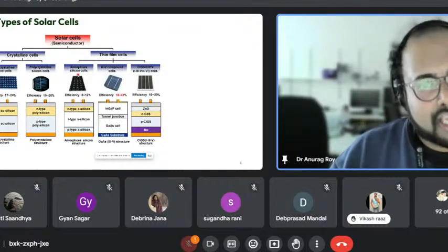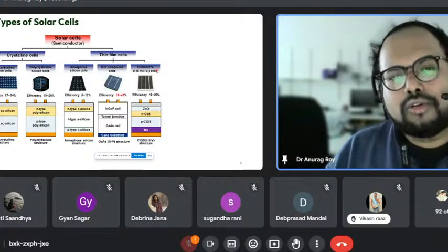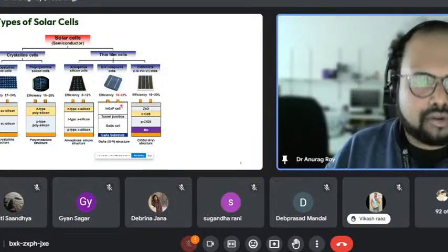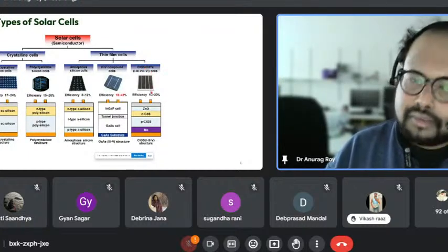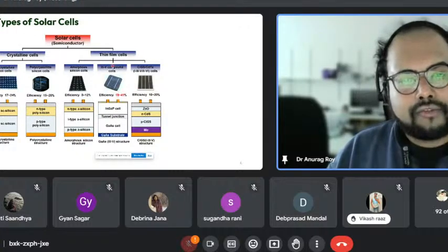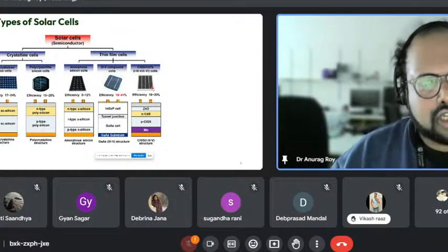And here is one interesting point: if you change the crystal structure of a semiconducting material, it can change the electrical efficiency as well. Another option is to not depend completely on silicon and go to some other materials, called group 3, group 5 compound-based solar cells in the periodic table. These can be indium gallium phosphide-based cells, gallium arsenide cells, CIGS, which is copper indium gallium selenide, and cadmium telluride cells. These cells are also available in the market, and they are also very good. They are called thin film based cells, and efficiencies lie between 18 to 41 for the 3-5 cells, and 10 to 20 for the others. Efficiency also depends on the way we produce the cells, how facilely we produce them, and how the atoms are oriented over the cells. That's also important. And you can see these are the basic structures of these cells.